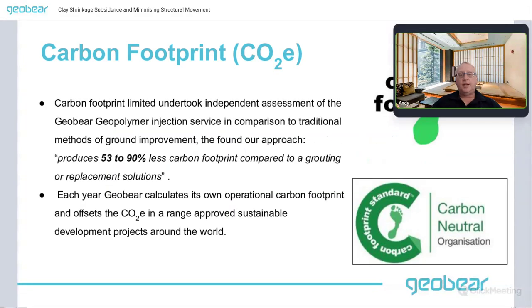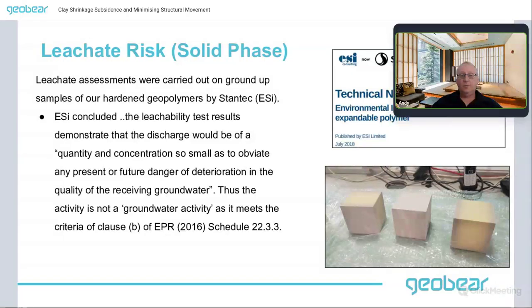General characteristics: the CO2 footprint of geopolymer solutions is generally lower than traditional cement-based options, maybe by about 50% in residential cases. It is inert. We've had it tested for leachate properties. It is safe to use over aquifers. It doesn't generate any harmful compounds in the dissolve phase.